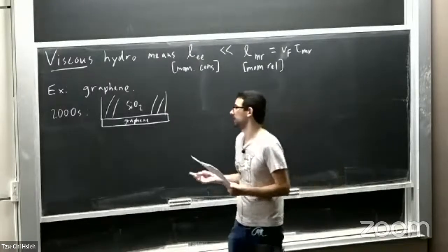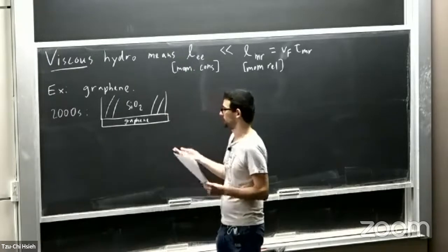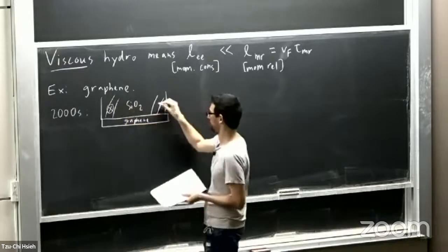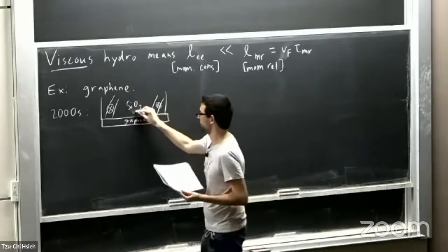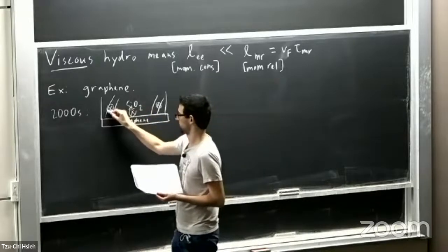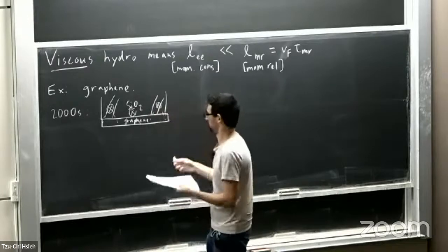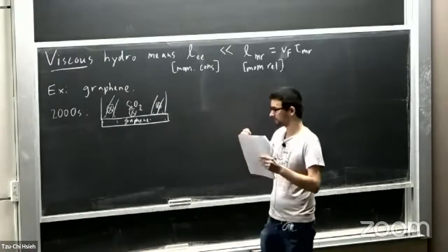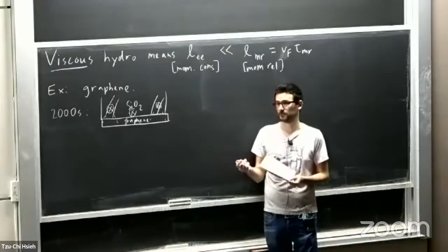Okay, both of these materials are maybe moderately pure, but there are some impurities, particularly in this glass substrate. For all of these impurities, these are typically charged impurities, and there are so-called charge puddles that form in the graphene layer. This will form the dominant source of disorder and momentum relaxation.